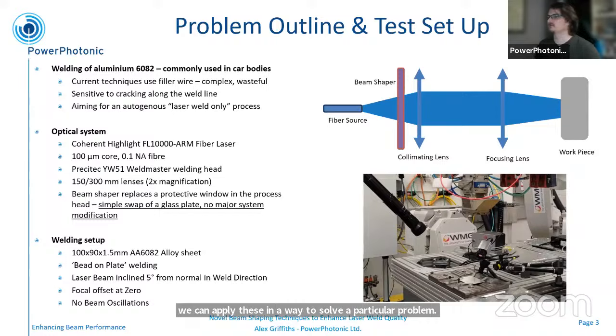The problem that we've addressed in this work is the welding of aluminium 6082. As has been mentioned, the welding of some of these aluminium alloys is difficult. The current techniques use filler wire, so you're adding extra material into the process. It's quite complicated, it can be quite wasteful. And 6082 is quite sensitive to cracking along the line that you're welding. So in this work, we're aiming to add some benefit through beam shaping to get a laser weld only process with no filler wire, and show some improvement in the issues around cracking.